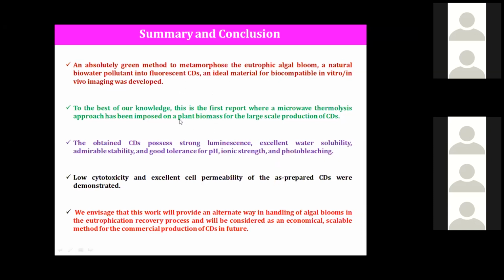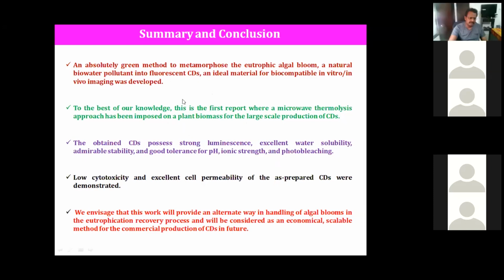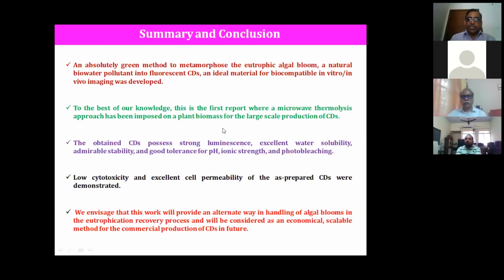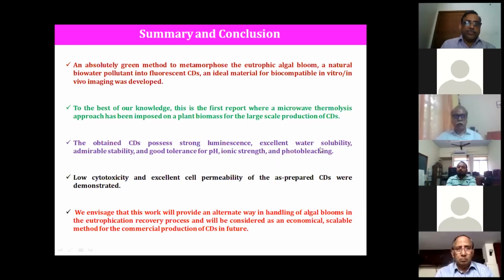To our best finding, this is the first report where a microwave thermolysis approach has been applied on plant biomass, and the obtained CDs possess strong luminescence and excellent water solubility. The solubility in water is a very important requirement when working on sensors and imaging, and we could see that with this carbon dot. We have admirable stability, good tolerance for pH, ionic strength, and also photo bleaching—it doesn't bleach when exposed to light.